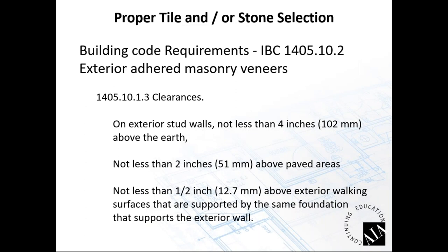On exterior, some of the other things that we have to take into consideration when we're hanging a veneer on an exterior application is your clearances at your ground level. On exterior stud walls, not less than 4 inches above the earth. In other words, we want to have that tile sitting up at least 4 inches above raw earth. If it's over a paved area, we're looking at no less than 2 inches. And if the wall and substrate bond together, we're looking at a minimum of 0.5 inch of clearance of the tile coming off the substrate. This is to allow for proper drainage of moisture getting in behind the tile, weeping down the walls and getting out of the system.